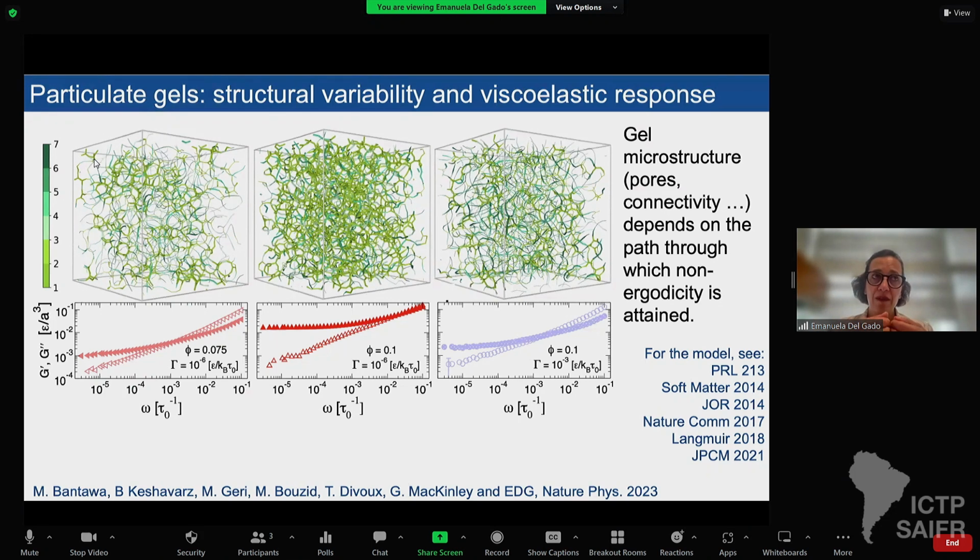What we also have in the model is that the interactions are written in a way that when particles start to stick together, there is also some resistance, or some price to pay, for the particles to roll over each other. This is to mimic the fact that the contacts between these particles when the gel forms can be more complex, due to heterogeneities on the surface of the particles, maybe different shapes of these aggregates, and adhesion that can happen at the surface of the particles.